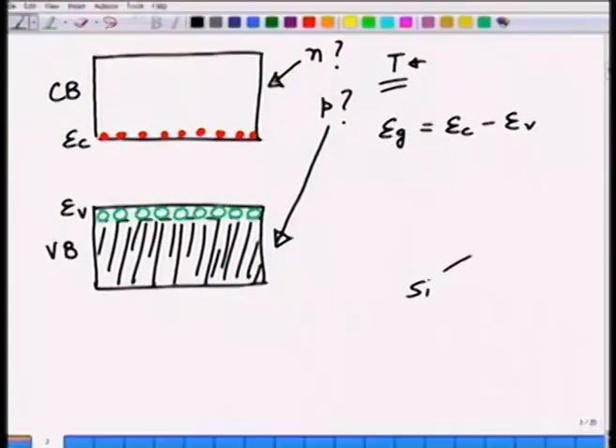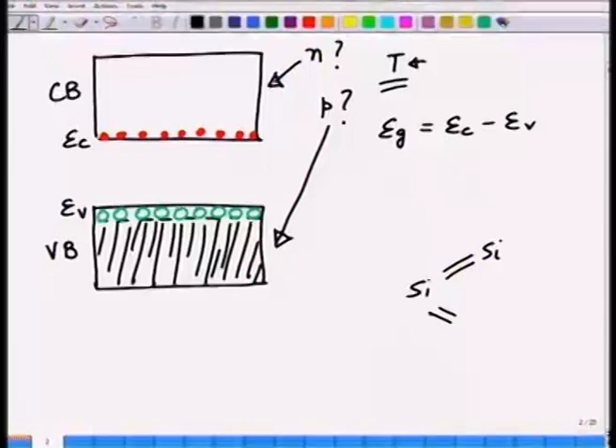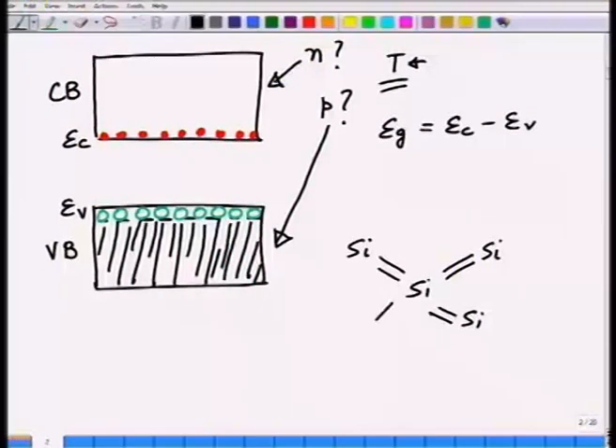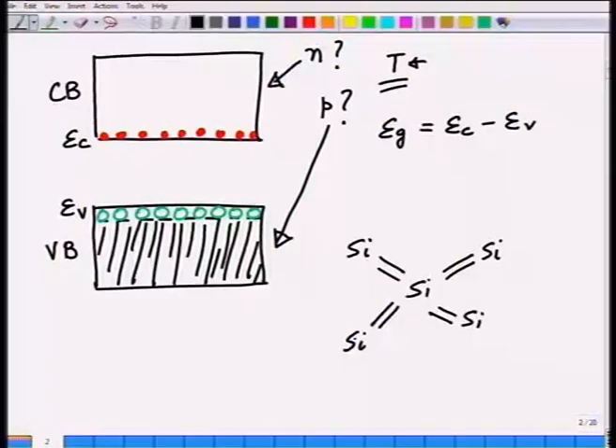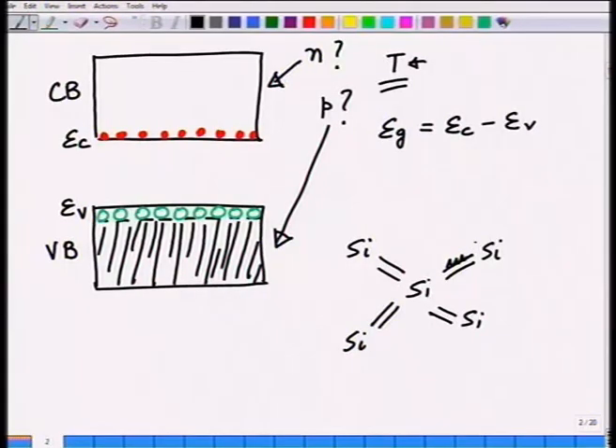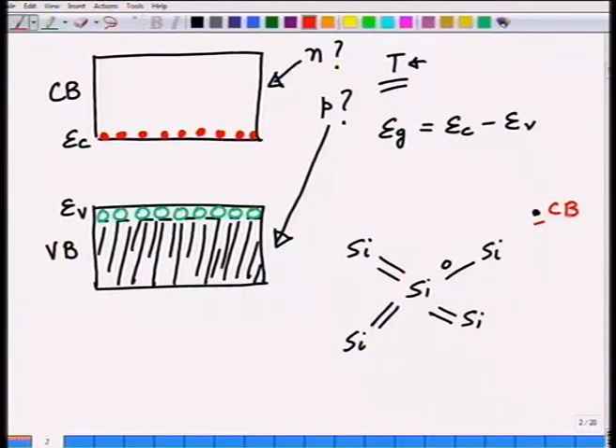In this context, you should also think like this: if you have silicon tetrahedrally bonded to other silicon atoms in fully covalent bonds, all electrons are tied up and they are all in the valence band. What happens when a bond breaks? I get a hole here and a corresponding electron becomes free — a free electron which goes into the conduction band, and this free hole is in the valence band.